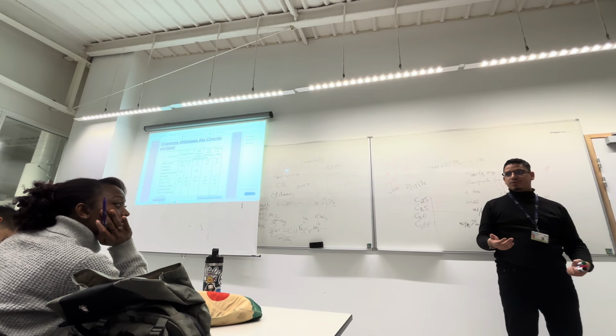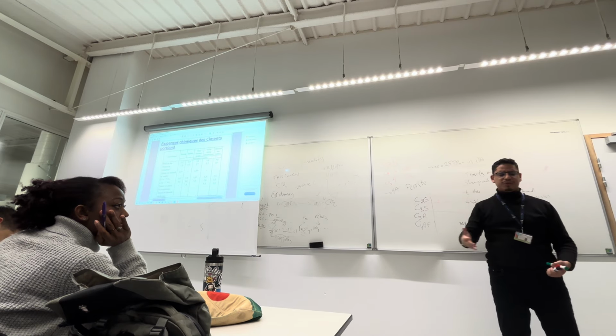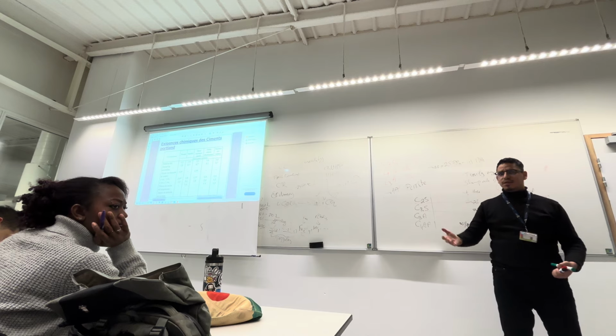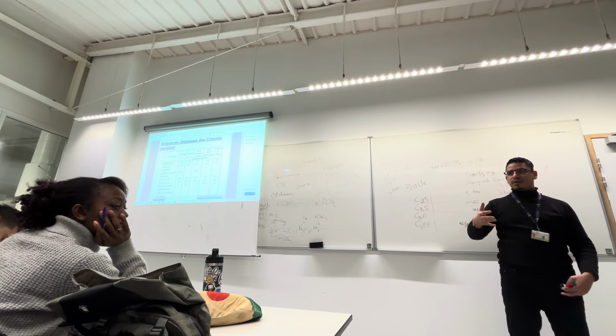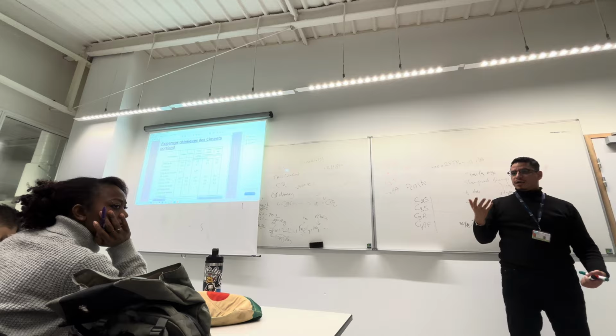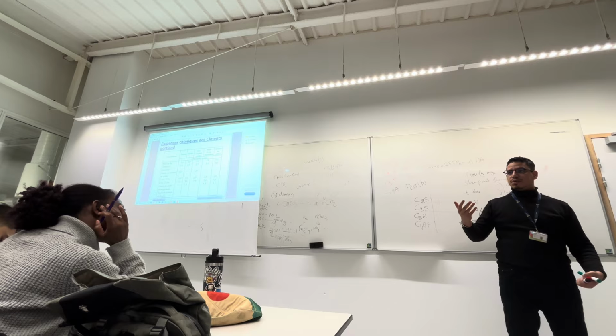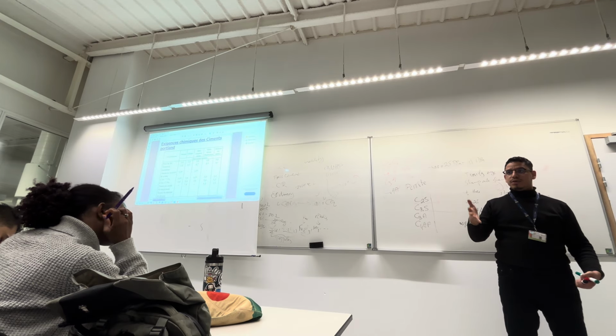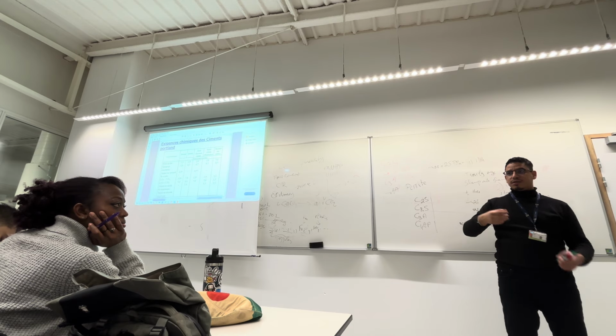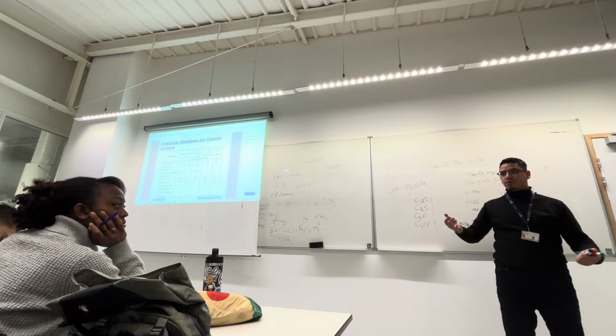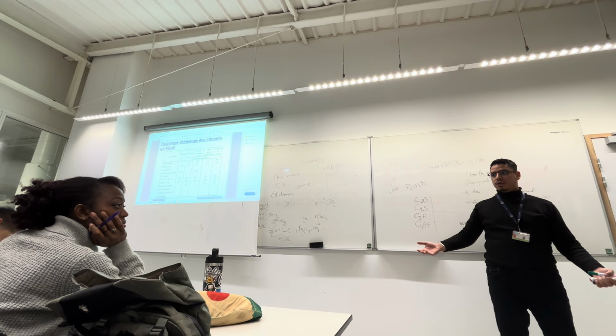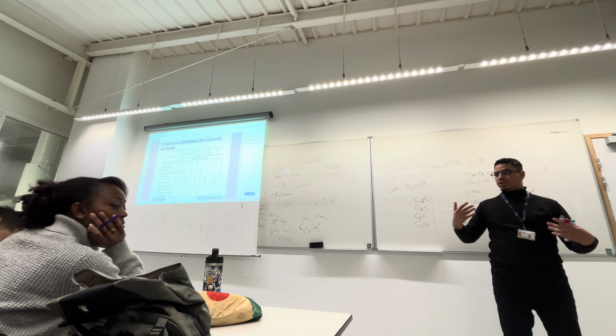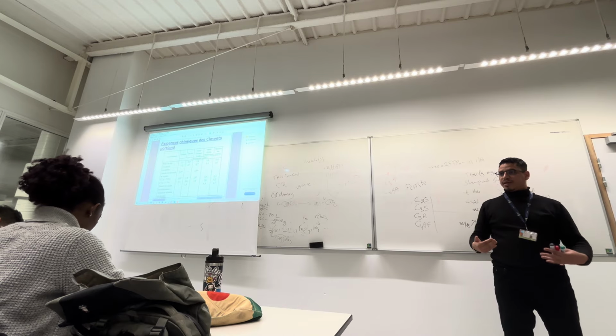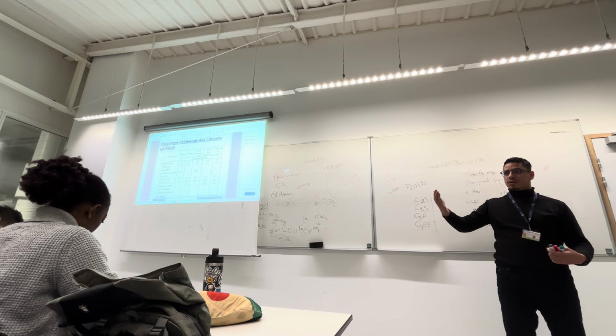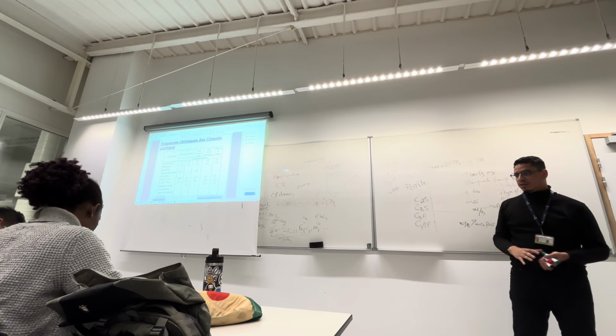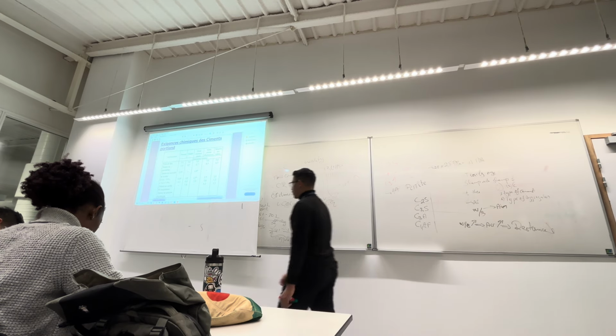Okay, for example, if we have a building, I think we call it offshore buildings, so the seawater attacks our concrete. Why we are interested in this attack? Because if the seawater penetrates into concrete, the chloride will react with the steel bars in concrete, and we have corrosion, and we have fracture, and we have failure. So we need to reduce the quantity of air voids, to reduce the permeability, and we reduce the attack of aggressive agents. Okay.